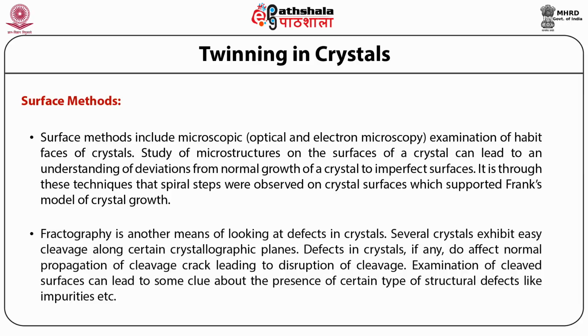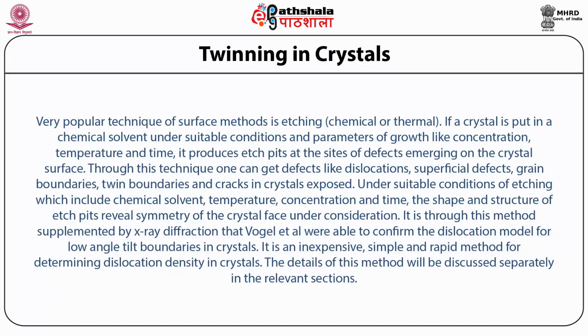Fractography is another means of looking at defects in crystals. Several crystals exhibit easy cleavage along certain crystallographic planes. Defects in crystals, if any, do affect normal propagation of a cleavage crack, leading to disruption of cleavage. Examination of cleaved surfaces can lead to some clue about the presence of certain types of structural defects like impurities, etc. A very popular technique of surface methods is etching, chemical or thermal.